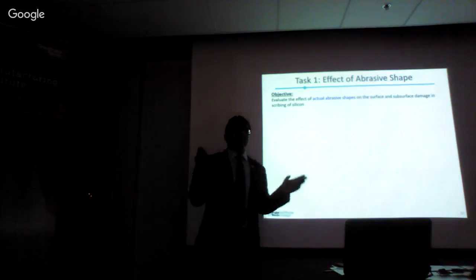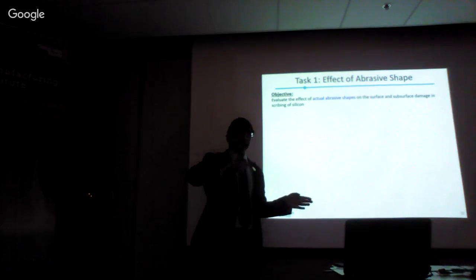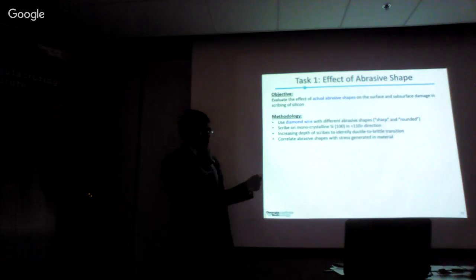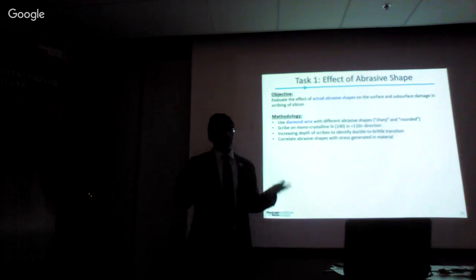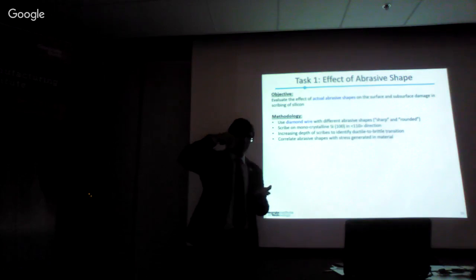The objective in this task is to find the effect of actual abrasive grit shapes on the diamond wire on the surface and subsurface damage during scribing of silicon using a diamond wire. So for the methodology here, we use diamond wire, which has different abrasive shapes. Some are round, some are very sharp, and some are in between. And we scribe on monocrystalline silicon material, which is of 100 orientation, and we scribe in the 110 direction. We use increasing depth of cut scribes, which means we start by just engaging the wire with the silicon and then go deeper into the material.